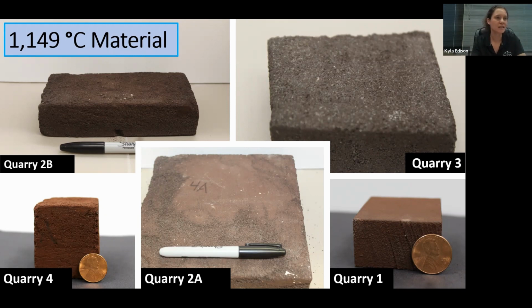After that test, we decided to go around and actually do the sampling around the island to see if we could get the same kind of material. And as you can see in these photos, there is quite a difference between all of the quarries that I sampled. Some of them are, I mean, clearly better than others. Quarry 2B, you can see it looks like if you were to touch it, it would fall apart. Same with Quarry 4, whereas Quarry 3 looks a little bit better. But Quarry 1 still definitely, in my opinion, looks the best.